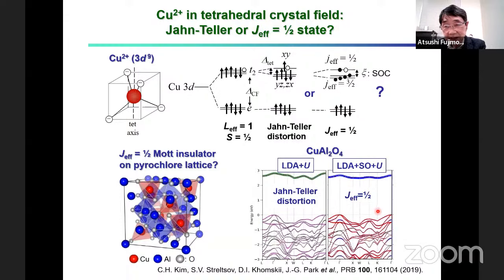LDA calculation, including spin orbit interaction, is quite consistent, but if there's a distortion, a Jahn-Teller effect, then one of the T2 levels is occupied by one hole. So whether the system is Jahn-Teller distorted or non-distorted, J effective 1/2, is quite subtle. The calculation can reproduce both cases depending on slight change in the lattice parameters or spin orbit interaction.